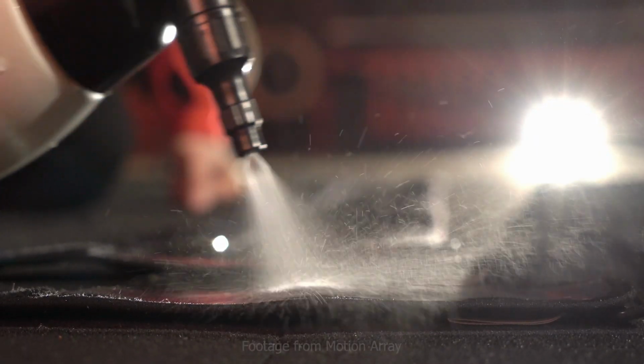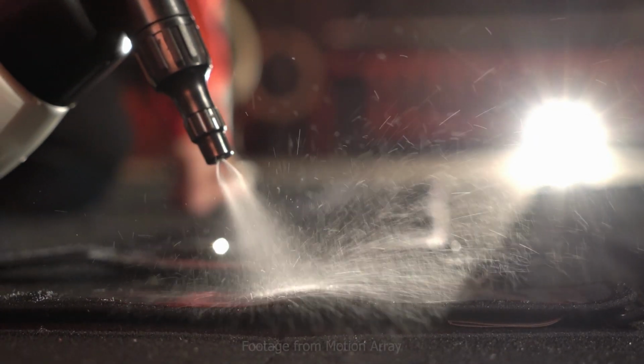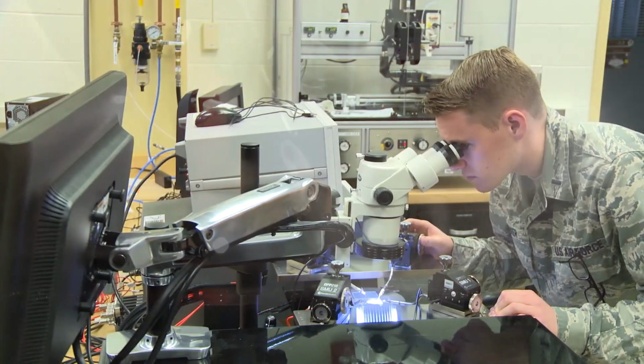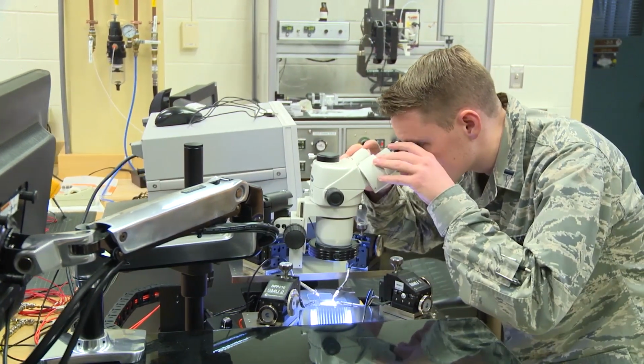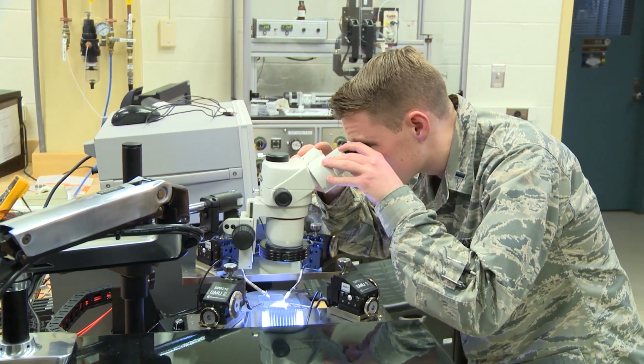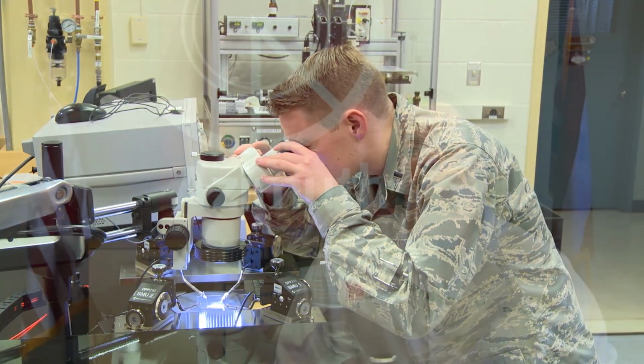Over the last 6 months of research, we have had tremendous progress. In this time, we have been able to develop multiple wet chemistry solutions to create a varying degree of viscosities for the coating application. The less viscous solutions allow for a very thin, highly crystalline coating to be applied. The highly viscous solutions, on the other hand, allow for application of the coating through a painting process and for a thicker coating with a more amorphous morphology.